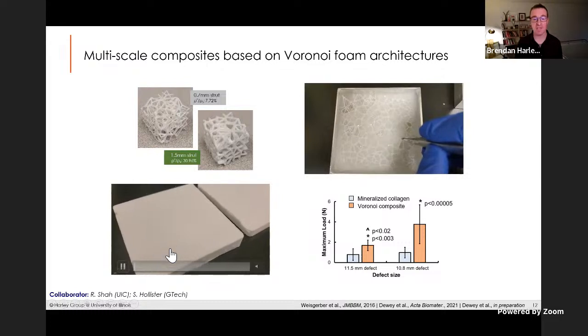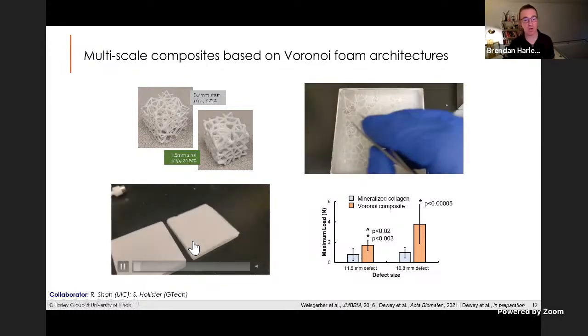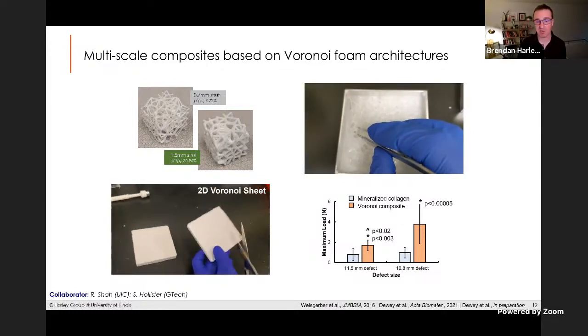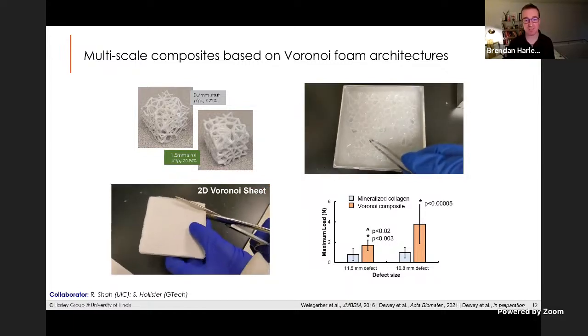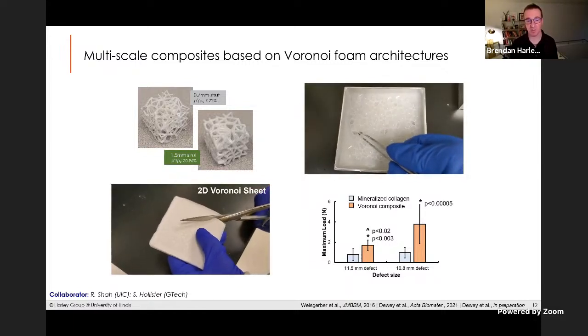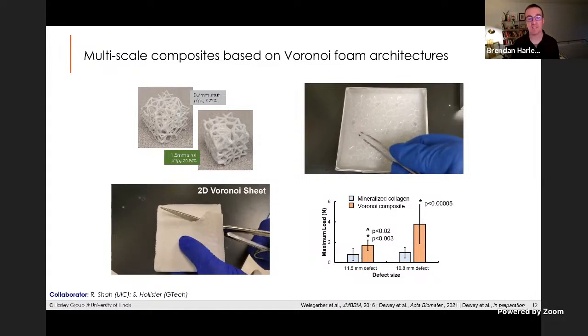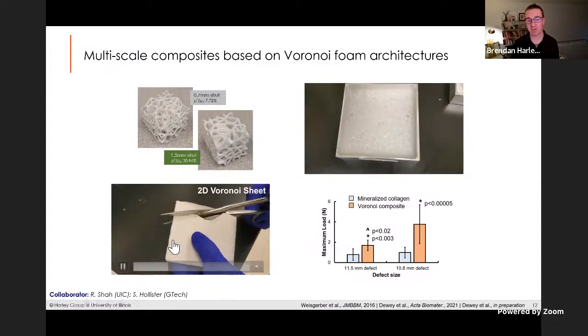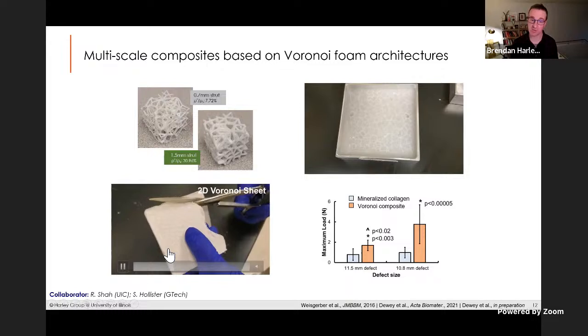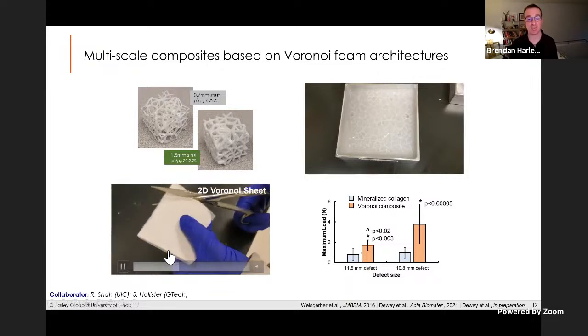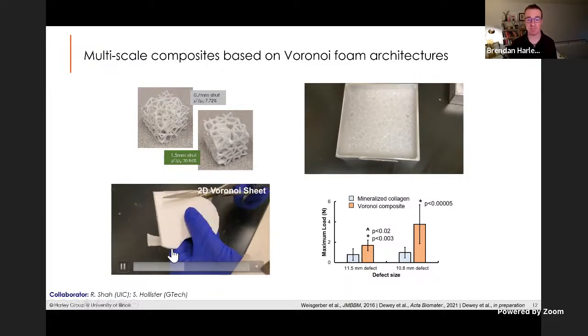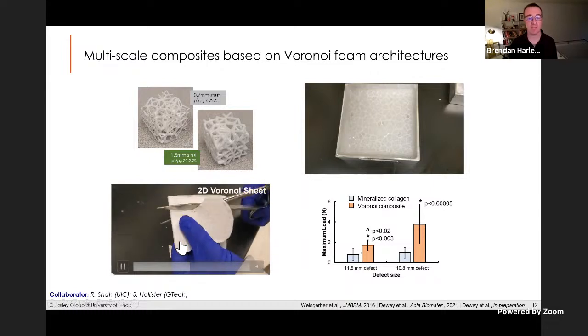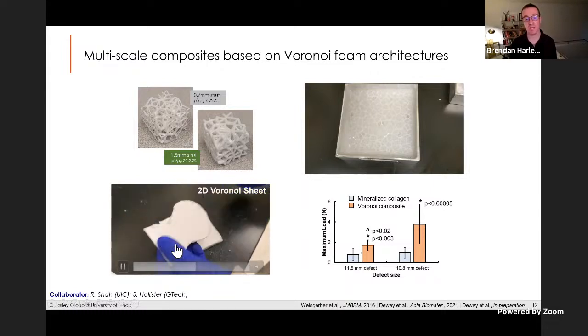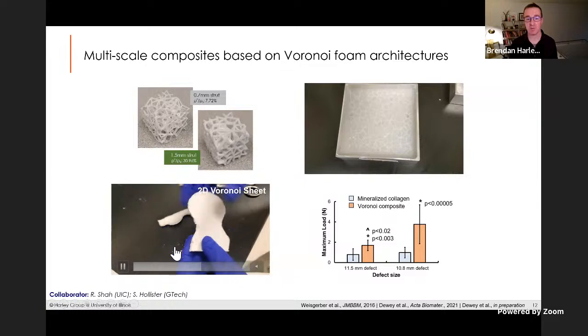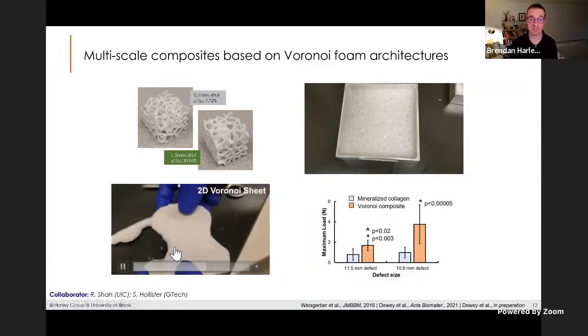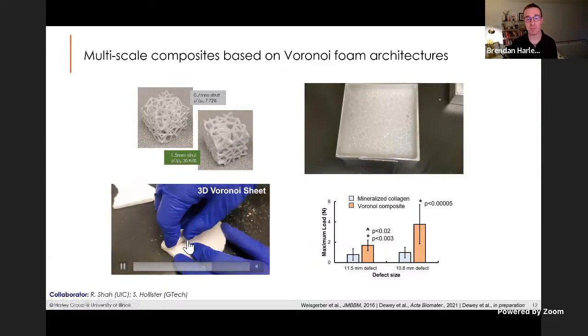And what you're left with is a material here on the bottom where it is a fiber array impregnated into our scaffold. So the scaffold is the part that drives the cells to do what we want, but isn't mechanically strong. But then we have these fiber architectures that are now embedded into the scaffold that make it strong, and also make it so that we can cut it and shape it. And the fact that these are based on these Voronoi foams means that as we cut and shape the implant, the mechanical properties of the smaller bit are the same as that of the larger bit. So we have properties that we can depend on.